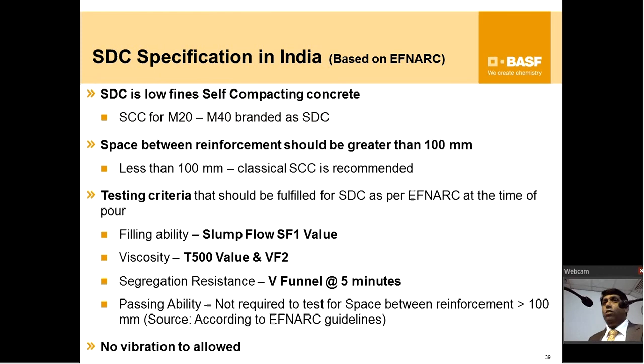Testing criteria: we test for filling ability, viscosity, segregation resistance and passing ability. This is as per the EFNARC guidelines. So SF1 value, VF2 and V funnel value at 5 minutes. Passing ability is not required to be tested if the space between reinforcement is greater than 100 mm. If it is less than 100, then you test it with the L box, the J ring, and other tests. No vibration is allowed. You should not tolerate any vibration, because if you vibrate this concrete, you will have segregation. So you do not allow vibration on this particular concrete at all.